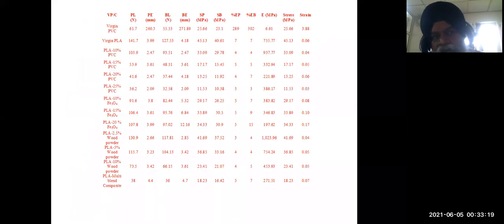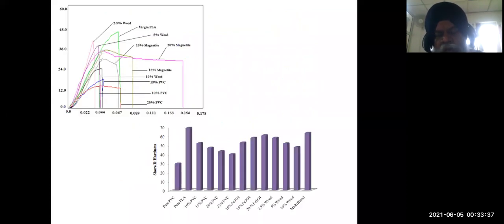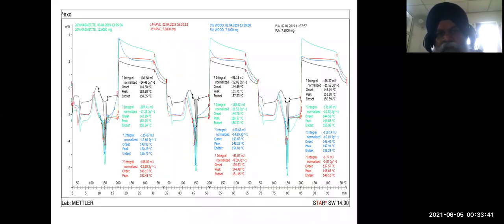So we played with the different levels of the reinforcement and tried to find out what is the peak load this material can take. Peak elongation, break elongation, peak strength, break strength, then percentage elongation at peak, percentage elongation at break, then Young's modulus and toughness. All these things we tried to develop, and some stress strain curves, their hardness relations. These things we were able to develop.